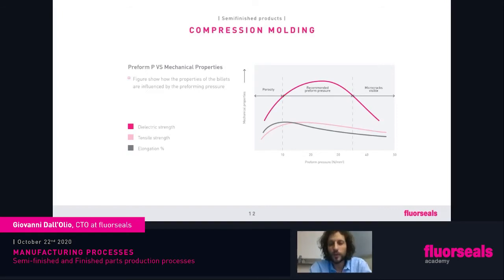So let's see what the graph is showing us. Basically, we have the preform pressure on the lower axis. In this case, we will take three examples: 10, 20, and 35. We are talking about newtons per square millimeter, which is the same as megapascal. If we are molding our shape at 10 megapascal, we will see these lines for the elongation, the gray line. We will have quite a good elongation. At tensile strength, the light pink line, acceptable tensile strength, but going to the dark pink line, we see that the dielectric strength is not the best.